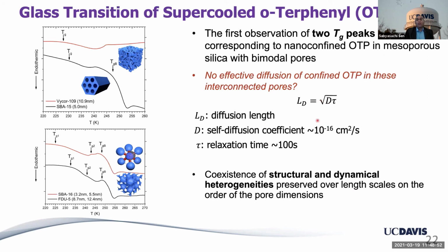So, on the order of nanometer scale diffusion length over the relaxation time, this could have homogenized and given us one TG, but it does not. Which says that there is coexistence of structural and dynamical heterogeneities that are preserved over these nanometer size length scales, or the length scales of pore dimensions. So the slow population and the fast population are remaining that way for time scales much longer than the average relaxation time. So, these kind of dynamical heterogeneities are also well known in the bulk.